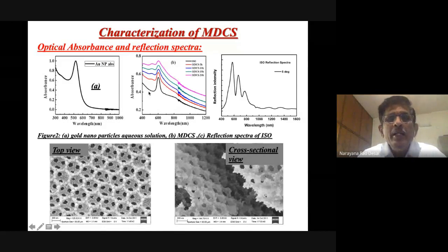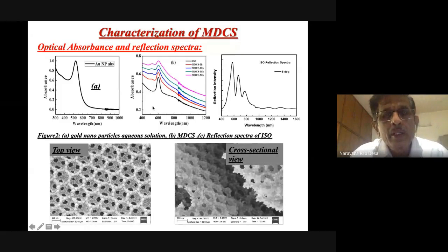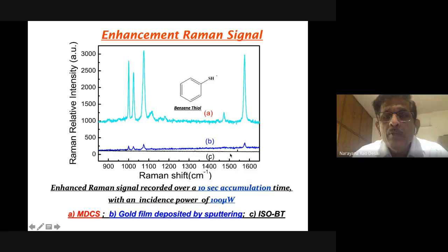Now we try to look at the Raman, and you see a beautiful Raman. This is your band gap of the photonic crystal. This is due to your surface plasmon absorption peak. Now you see the Raman with an inverse silica opal with benzene thiol, whereas this is on a gold film and this is on a photonic crystal. You see a beautiful enhancement in the Raman signal.